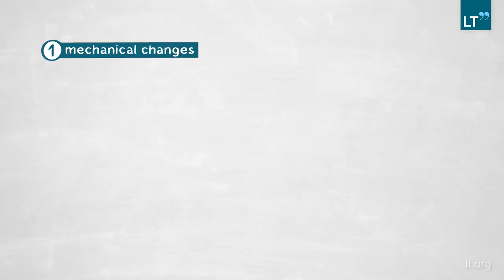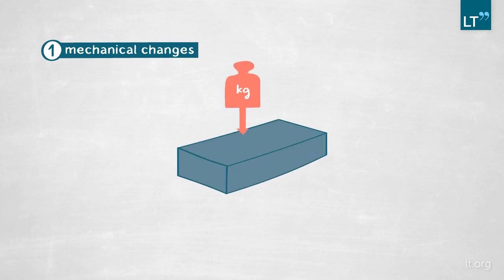But what about hydrogen? For that, we develop our own in-house in situ hydrogen charging cell. This is basically an electrochemical cell that is placed beneath our sample, and we produce hydrogen in there by using the hydrogen evolution reaction, and the atomic hydrogen will further move towards the upper testing surface for nanoindentation. This particular method that we are developing will allow us first to track particular changes in the mechanical behavior that are related only to the presence of hydrogen. And this is because no other effects are expected on the sample surface.